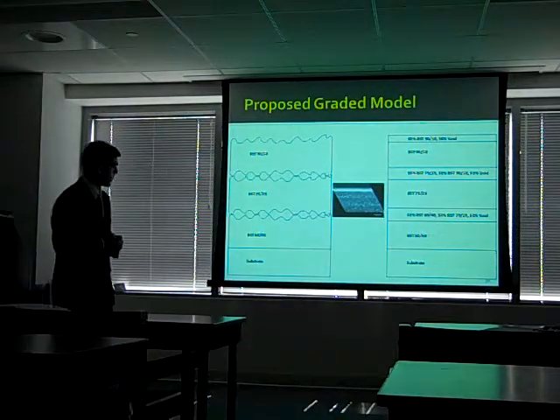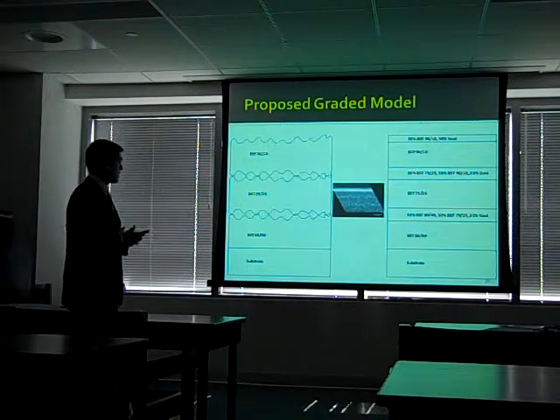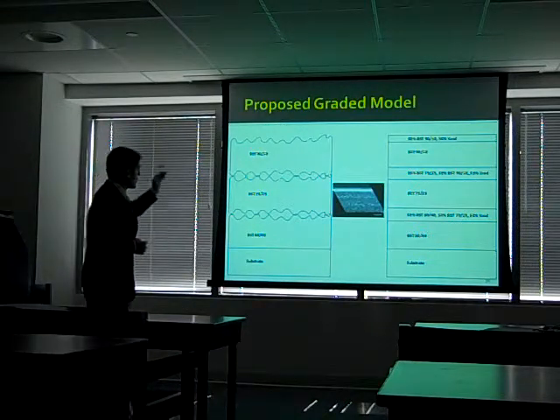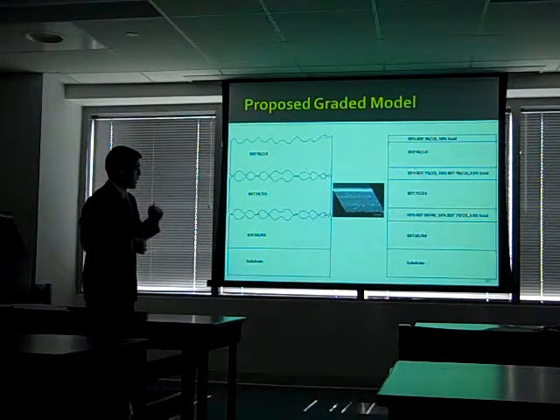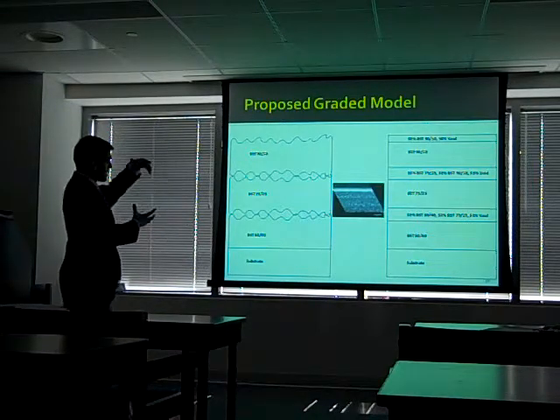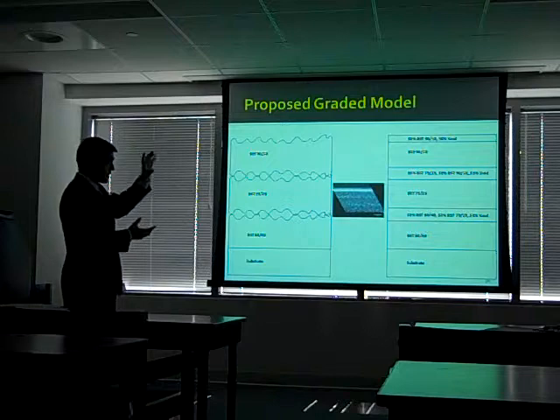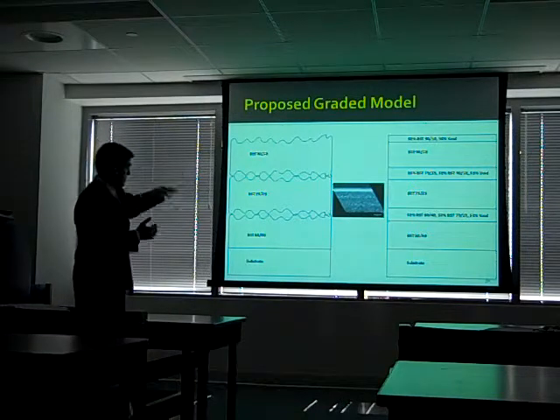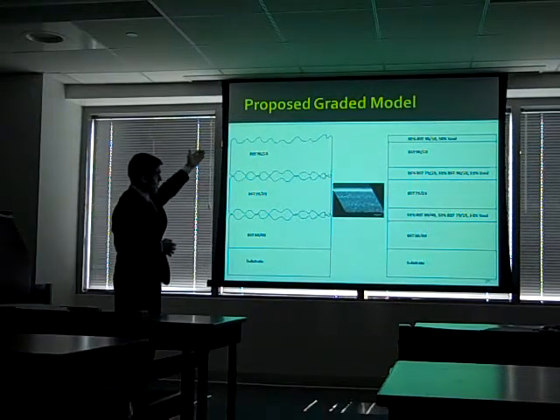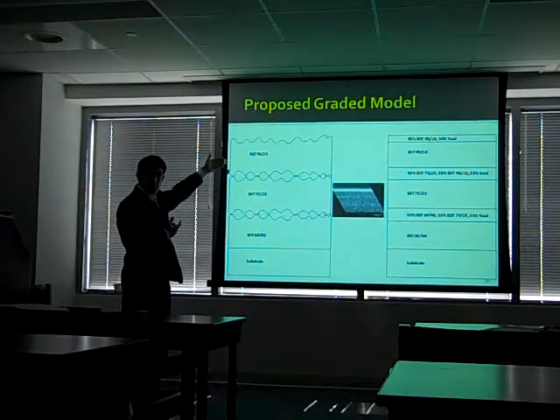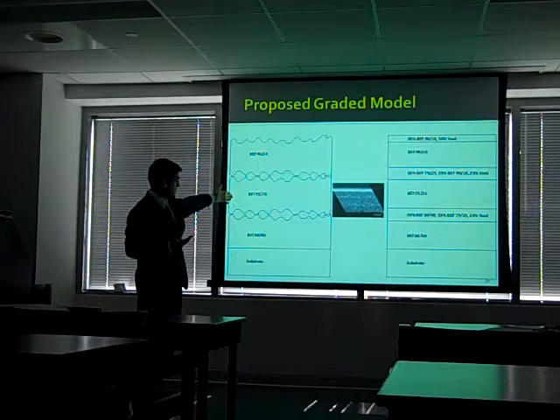So from analyzing that, I came up with the following model, which you can see is a lot more complicated. So when you have roughness in a film, you'll model that. Again, you have to have parallel interfaces. You model that as a mix of 50% void and 50% of the material that is the roughness. So that's the top layer. The interfaces will be 1/3 of the top composition material, 1/3 of the bottom composition, and 1/3 void in the middle.